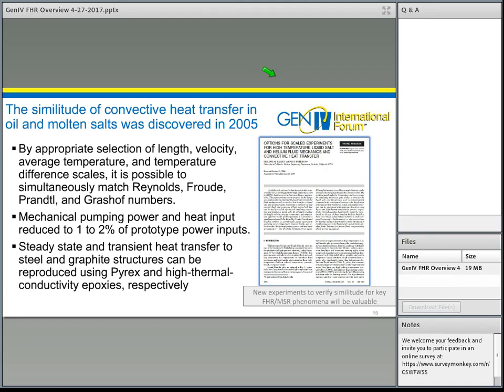The heater power is 1.6%. And that means, for example, a 10 kilowatt experiment using oil is comparable to a 600 kilowatt experiment using molten salt. And with this, one can study not just the convective heat transfer, but if you select correctly the scaled properties of the solid structural materials, you can also scale to match transient heat transfer and response to heat structures as well.